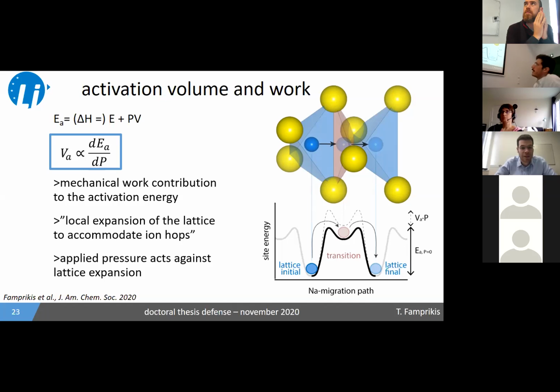Sometimes you break the activation energy into the migration and the enthalpy or energy of formation in any case of mobile defects. And these days, in the popular literature, we're really mostly talking about EM. We're not considering that we're making defects in this material. We consider that these are somehow in the extrinsic regime. Okay, so your measured activation barrier is really the migration enthalpy plus 1/2 of your defect formation enthalpy.